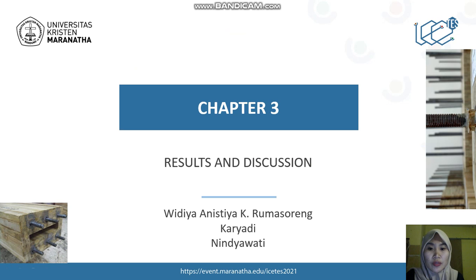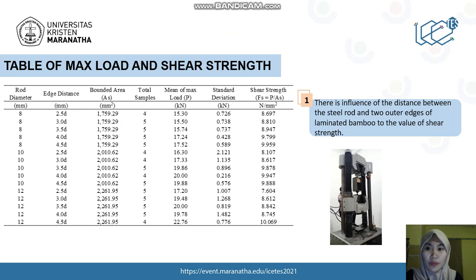We move on to chapter 3, result and discussion. This is the table of maximum load and shear strength. This table shows the data of rod diameter, mean of maximum load, edge distance, and the shear strength. From the table, there is influence of the distance between the steel rod and two outer edges of laminated bamboo on the value of the shear strength. We can take an example at the same diameter 8 mm: the greater the edge distance, the greater the shear strength calculation result.